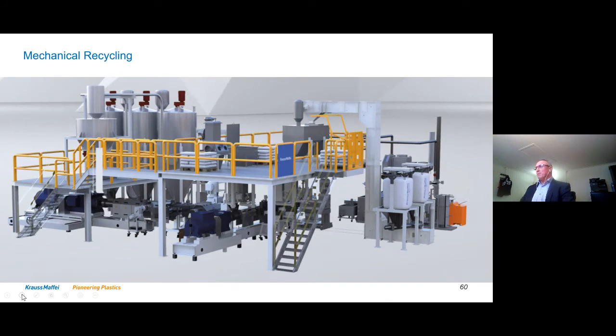So this is a simple, let's say, picture of a mechanical recycle line, where at the left side you see our plastification extruder, where the feedstock, based on rigid flake and agglomerated films, is fed to the extruder, being molten, being degassed, being filtered by laser filter technology, and that stream of melt we feed into the second extruder, the cascade, where we can then add mineral fillers, glass fibers, additives, and make a final compound in one step. Next slide, please.